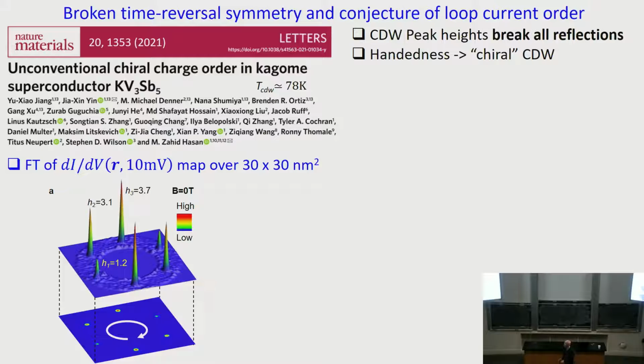So you always have sort of a three C2 axis. But all reflections are broken. You can do a reflection along any of these 3 axes, that's broken. If all reflections are not there, you have a handedness. So in this case, if you go from weak to intermediate to strong, left-handed. Right? There is a left-handedness in the intensity of the CDW peaks. We don't know what that means. It's never been talked about in physics, what this intensity difference would mean.